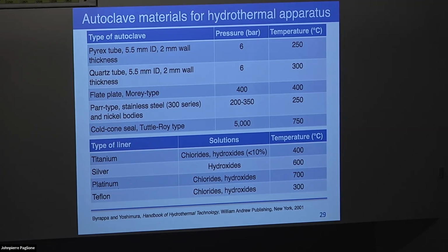So you need to have something that's completely inert to whatever your system is. For example, Teflon is pretty much the most commonly used. It's pretty inert to chlorides and hydroxides and pretty strong acids as well. The problem with Teflon is it starts to deform. I think this 300 is a little bit ambitious. It starts to deform at about 250 C. And when the liner starts to deform in your autoclave, it starts to not be able to hold pressure.